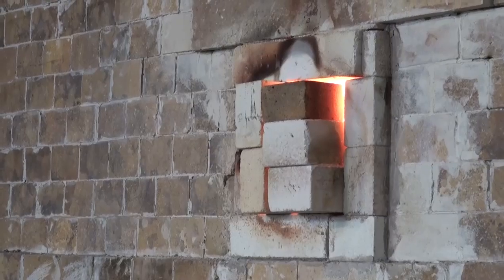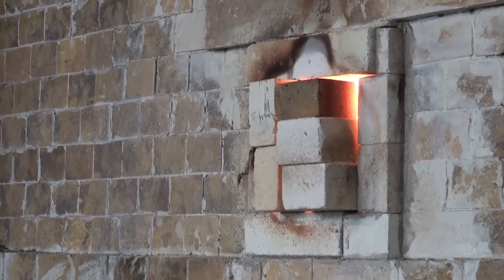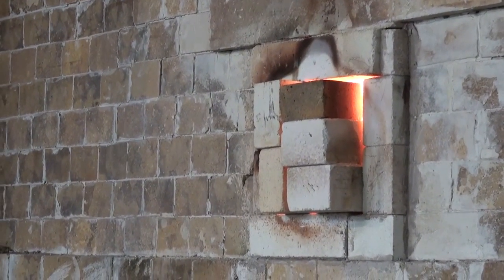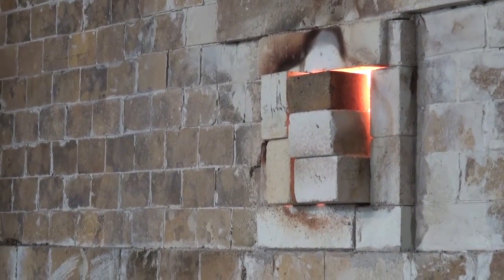In the final stage, the glass is cooled by forced air cooling from 1200 degrees to 1100 degrees by blowing cold air on its surface, and the temperature of the glass at the end of that process is very carefully controlled by automatically adjusting the air, and it keeps the glass at a very constant temperature, close to 1100 degrees, ready for pouring onto the molten tin.